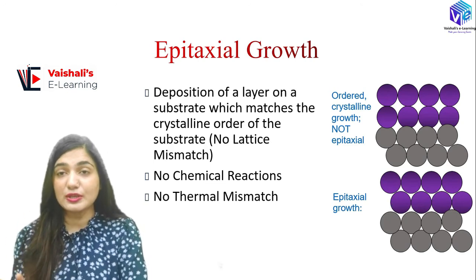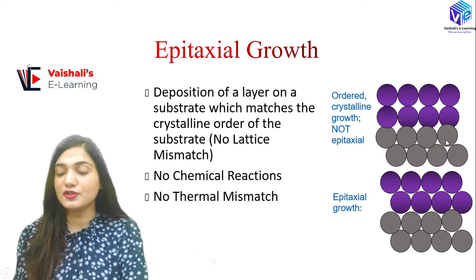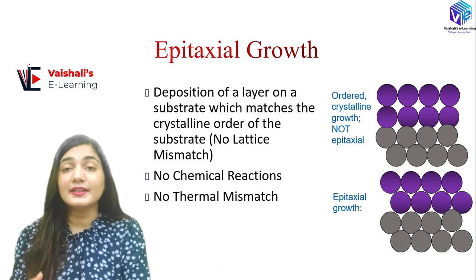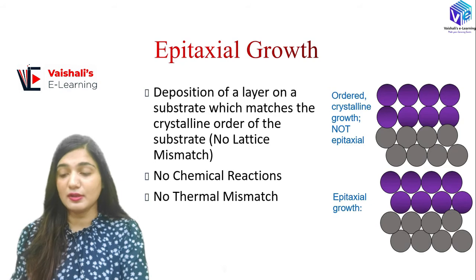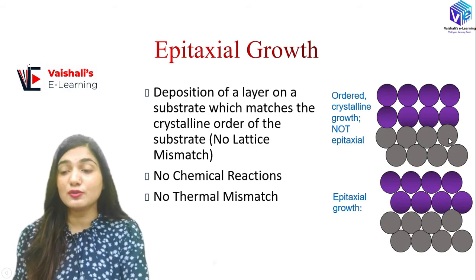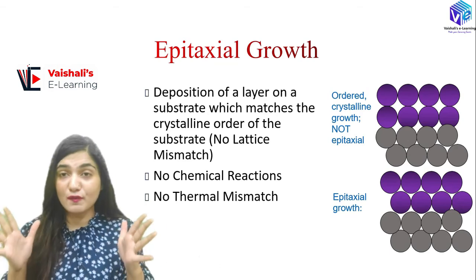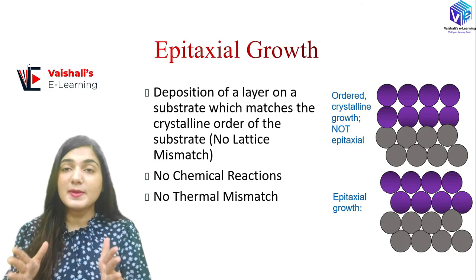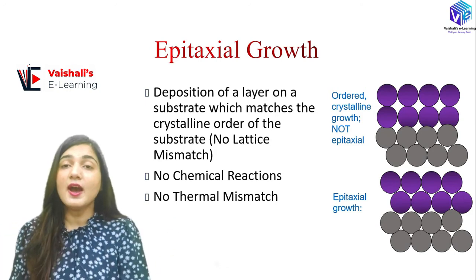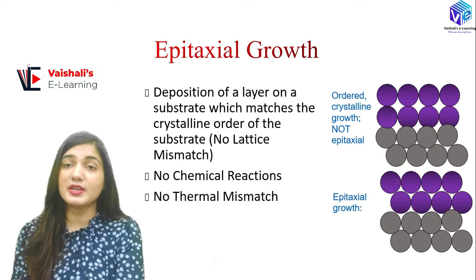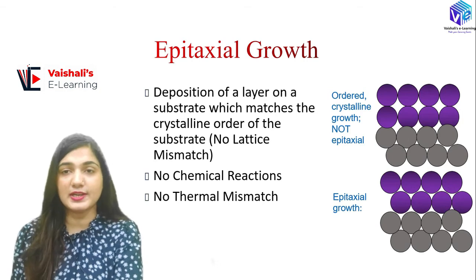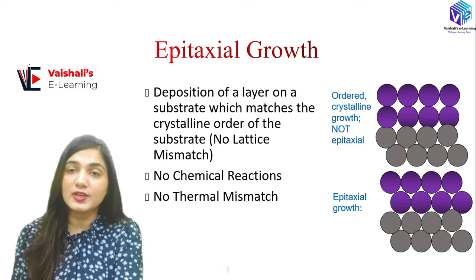There are three requirements for epitaxial layer classification. First, deposition of a layer on a substrate that matches the crystalline order of the substrate. Second, there must be no chemical reaction between the deposited atoms and the substrate atoms — a chemically reacted layer is not an epitaxial layer. Third, there must be no thermal mismatch between the epitaxial layer and the substrate, so that high-temperature processing does not cause differential expansion and damage the device.